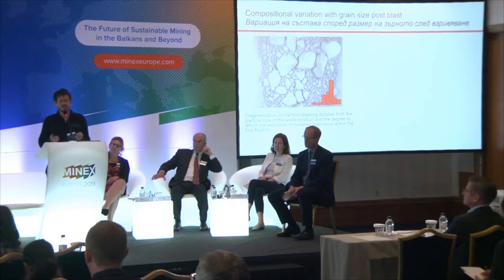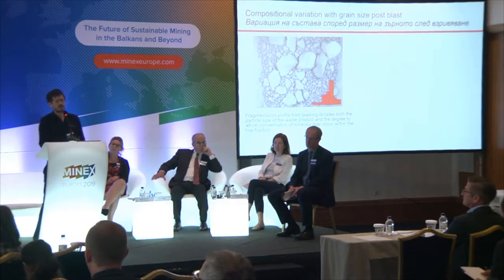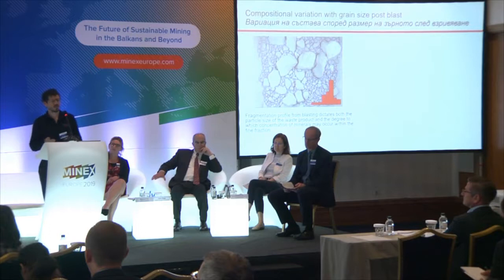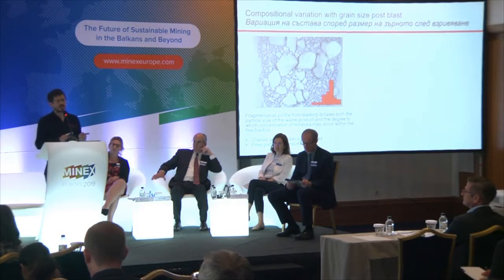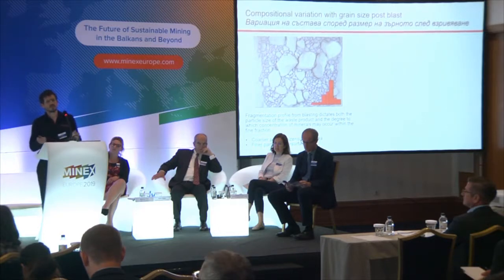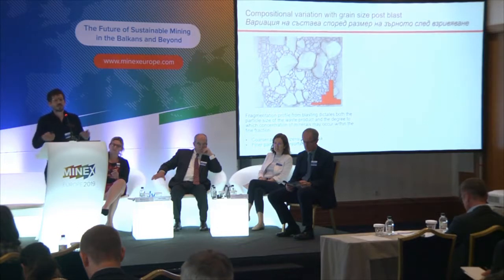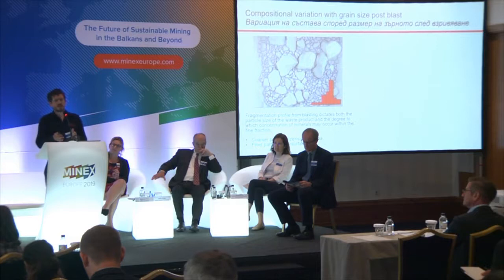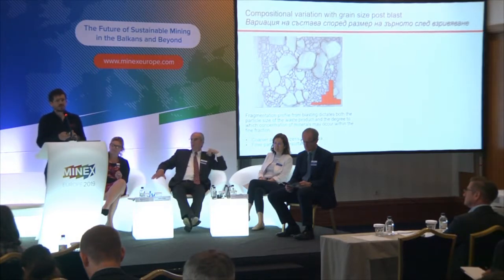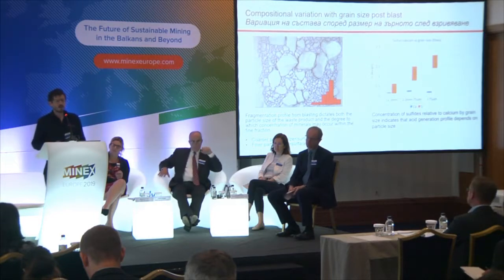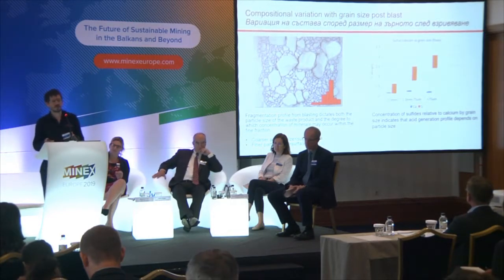So if we look at compositional variation with a blast, the fragmentation profile is important because it dictates both the particle size of the product and the degree to which concentration of metals can occur within the fine fraction. Coarser particle sizes have a smaller surface area, finer particle sizes have a bigger surface area. The reason why that's important is that the surface area influences the speed of the reaction of sulfides with oxygen, which is where you get acid mine drainage from. So, like I said, the finer fractions, they're smaller, they have a higher surface area, they are much more reactive. If we're also getting concentration of sulfides into those fine fractions, it doubles the problem up.